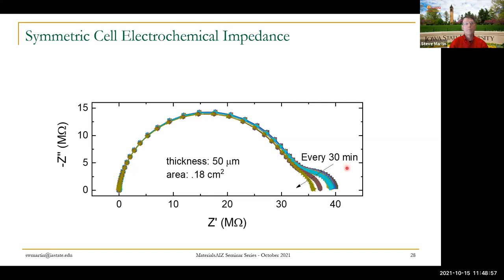And here now we're measuring for the very first time a 50 micron thin fast ion conducting glass. All the work I've reported over many, many years has always been on the thick samples, 1 to 2 millimeters in thickness. And here you can see we can do a symmetric cell, lithium, glass, lithium. As expected, there's a little bit of interface, but that interface decreases with time. And this is across 50 microns. Remember, a human hair is about 100 microns, so this is half the thickness of a human hair.